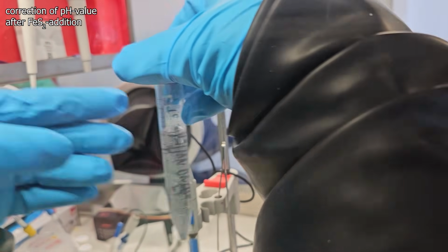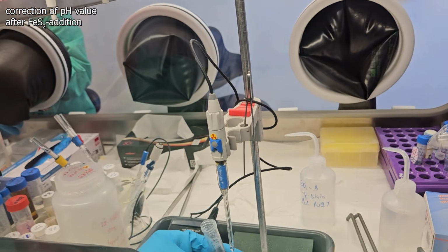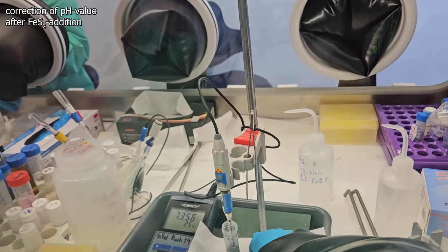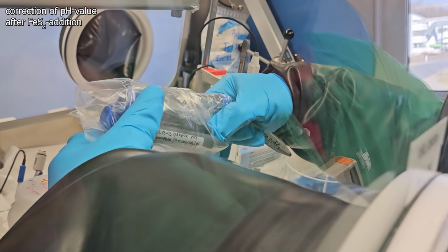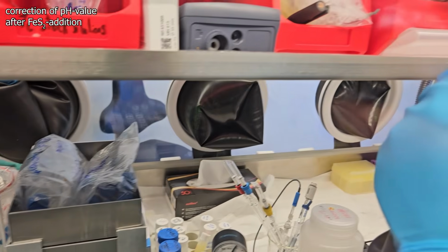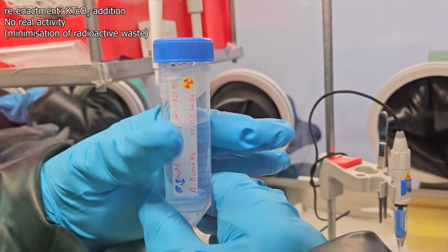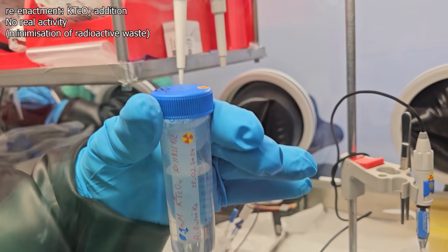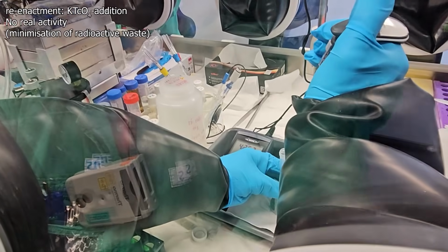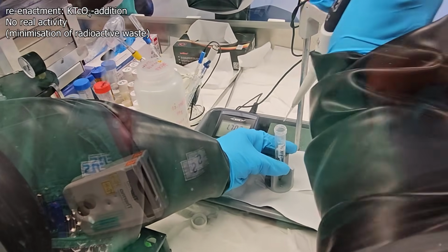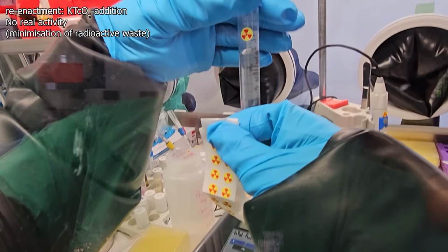For longer experiments, the entire system must be shaken, and as an extra protection, bags are placed around the Falcon tubes again because technetium contamination is really annoying. This is the potassium pertechnetate stock solution with a concentration of 0.1 millimolar. If this is added, the whole mixture must now also be labeled as such afterwards.